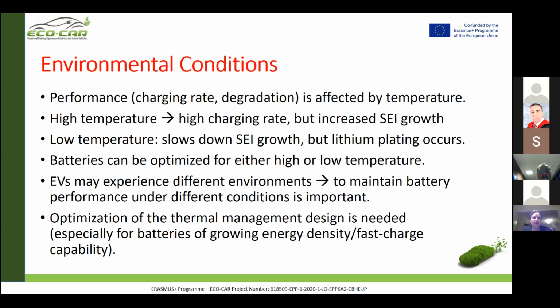Environmental conditions are very important. The performance of the battery, the charging rates, and the degradation are of course affected by the temperature, as said before. At high temperature, we have a high charging rate, but the solid electrolyte interface, which is not desired, will grow, and also some other undesired side reactions will take place. At low temperatures, the solid electrolyte interface growth slows down, but instead lithium plating occurs. That is also not desired.